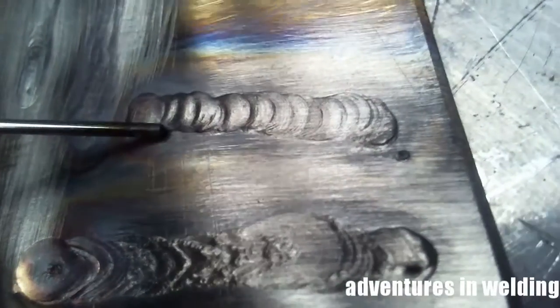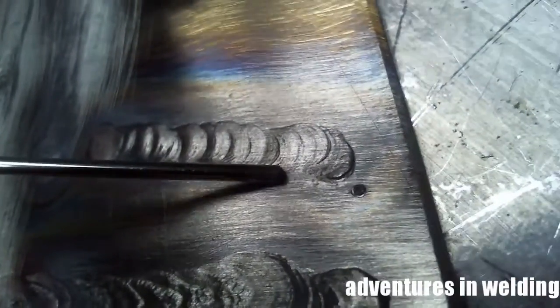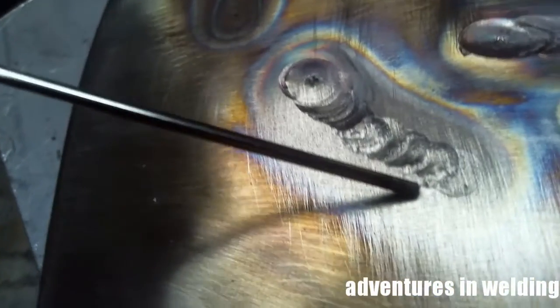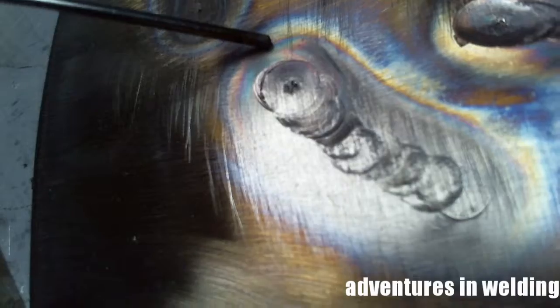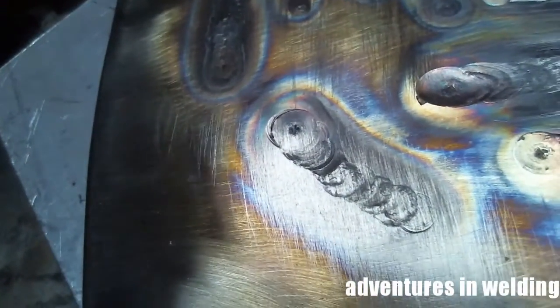Then we came adding some filler metal, and that's really nice looking there at about 45 amps or so. We cranked it up to 50, too much, burnt. Back down to just about 40, maybe about 45 or so. And then finally, right back to 40. Nice color, everything looks good. So there's telling you some stuff about the stainless steel. Everything about watching your heat, that's the most important thing.